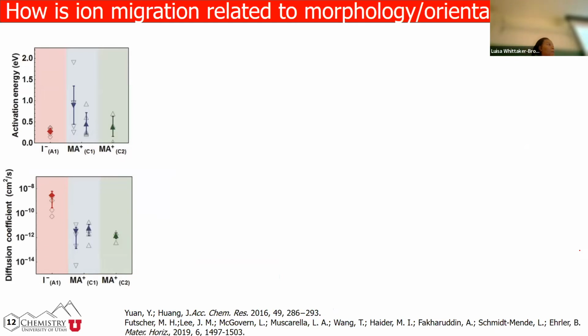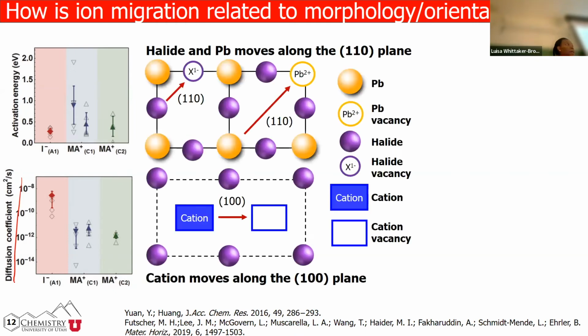So we are not theoreticians, but we actually like to use models very well. So we went and calculated the activation energy of these materials in terms of ion motion. Metal halides are ionic materials where you will see a lot of ions moving. The iodide has an activation energy that's pretty low, about 0.3 eV. The methyl ammonium cation is higher. Lead is about 2.2 eV, so we actually don't talk about lead migration. That's just too heavy, okay? And that correlates with the diffusion coefficient. The iodide has a higher diffusion coefficient. So we know that iodides are going to be moving over the organic cation.